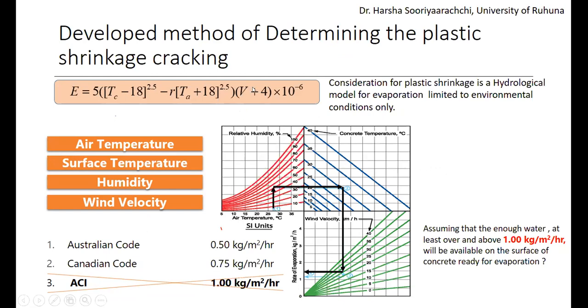This equation model was developed by ACI, the American Concrete Institute. They developed this E, which means evaporation rate index, TC means concrete temperature, R means relative humidity, TA means ambient temperature, V means wind velocity. Those are the four key factors that govern plastic shrinkage cracking. So ACI said that if I want to make a concrete now, I can measure the concrete temperature, the air temperature, the humidity condition, and the wind velocity of the particular area, and with that I can predict the evaporation rate index with this equation.